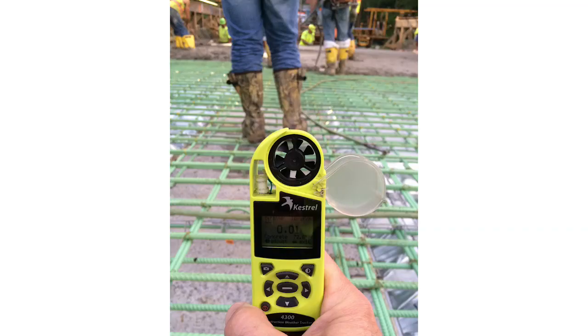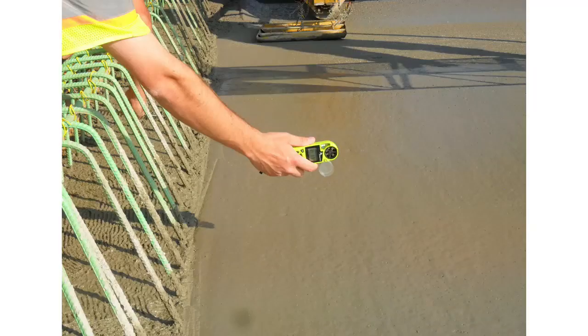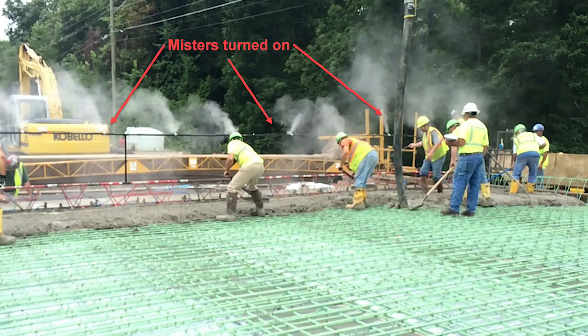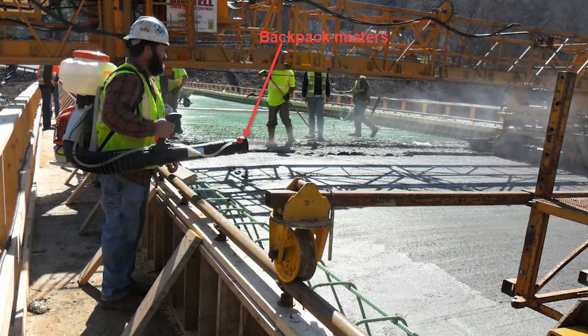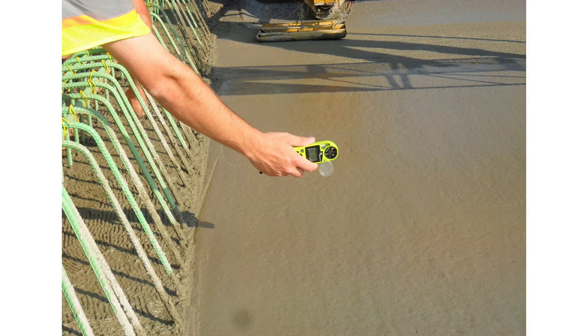Evaporation rates for bridge decks, as per Publication 408, Section 1001.3. Do not exceed an evaporation rate of 0.06 pounds per square foot per hour before starting the deck placement and every hour during the placement. If the evaporation rate value is exceeded, stop the concrete deck placement until protective measures are taken to reduce values to an acceptable level.